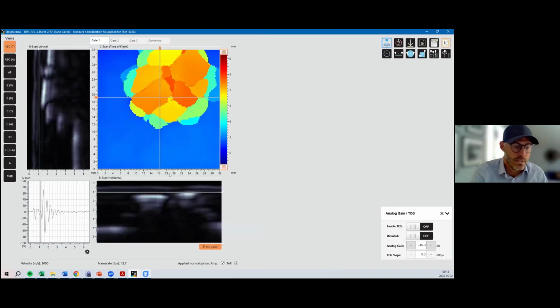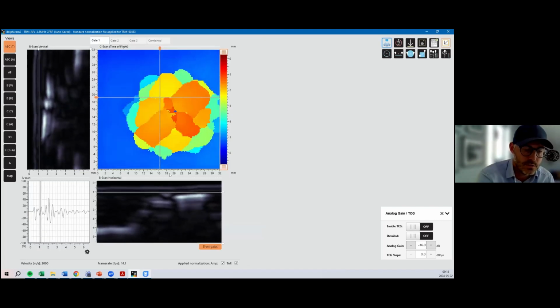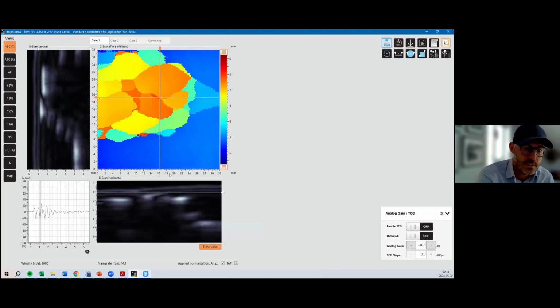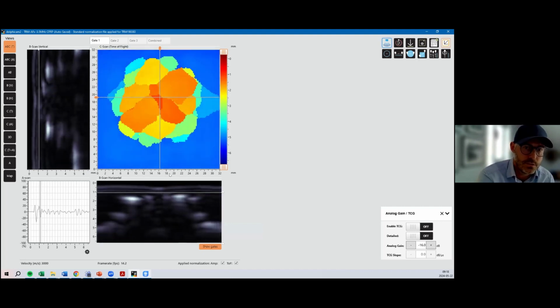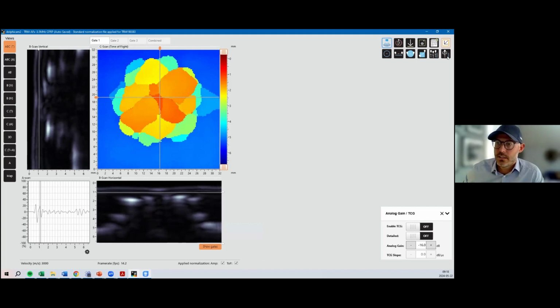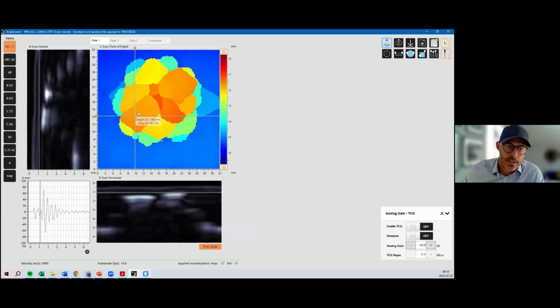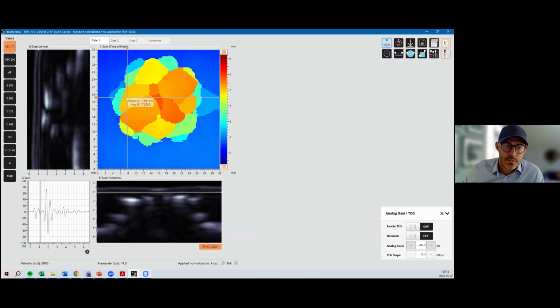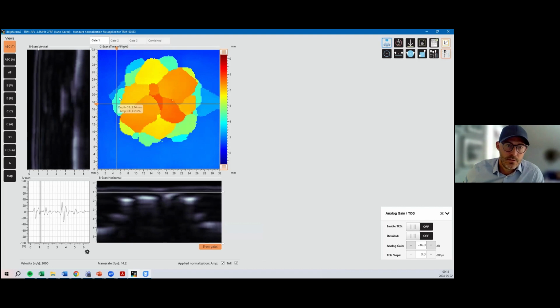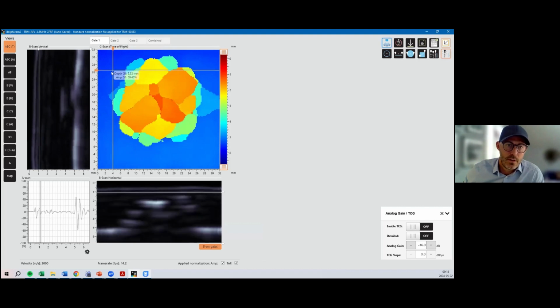And then if I go to time of flight only, which is this blue one here. So blue, everything is fine. Colors, you have damages. And in this case, I can enable the depth here. I can see that this part here is 1.69 millimeter. This is 1.96 and so on, 3.7, and the back wall here is 5.3.